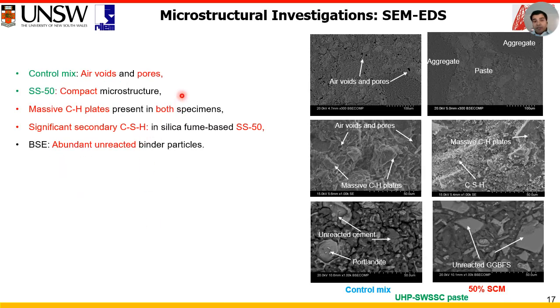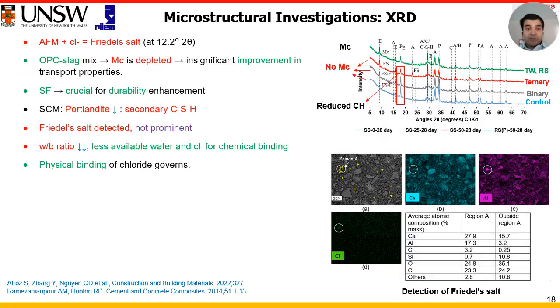From the microstructural characterization, we found that the 50% SCM based ternary mix produces a much more compact microstructure without any visible pores compared to the control. We could see an abundance of CSH gels, and also the unhydrated binder particles were abundant within the microstructure.